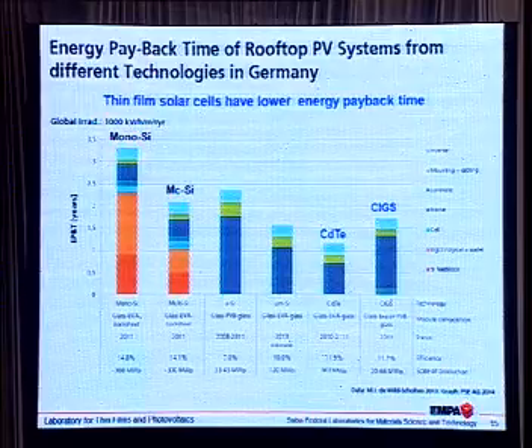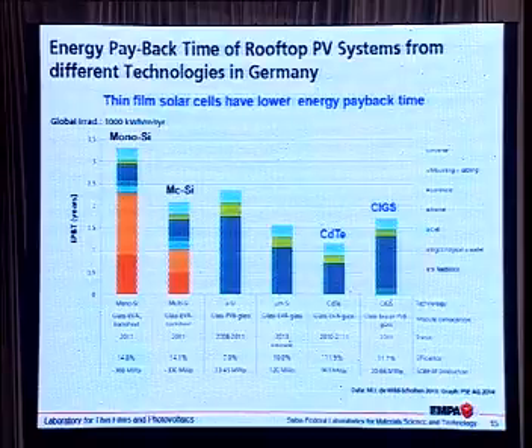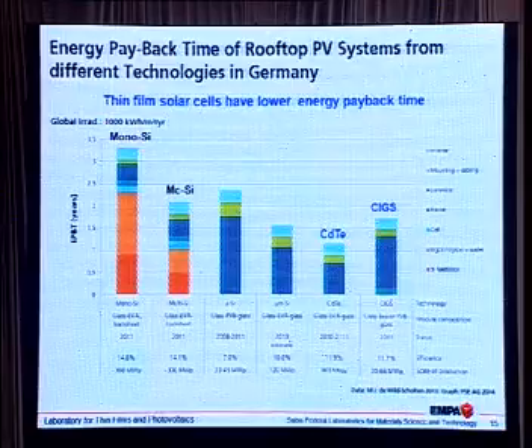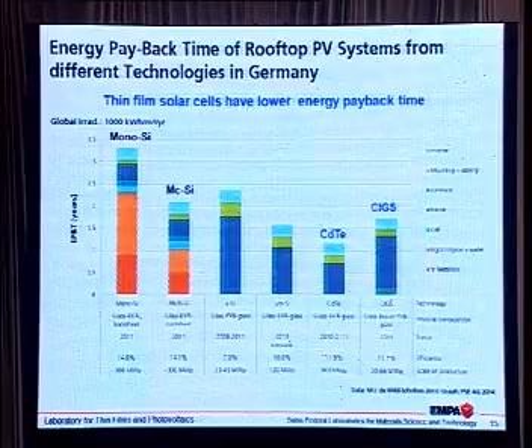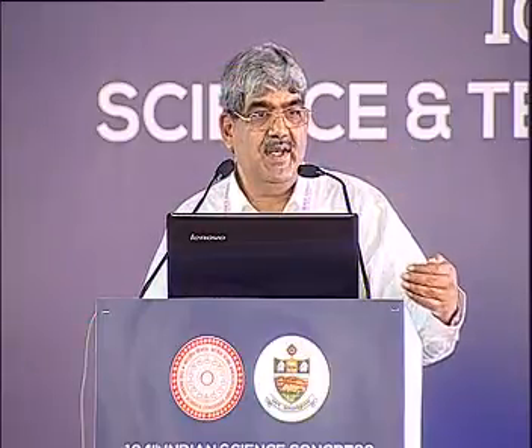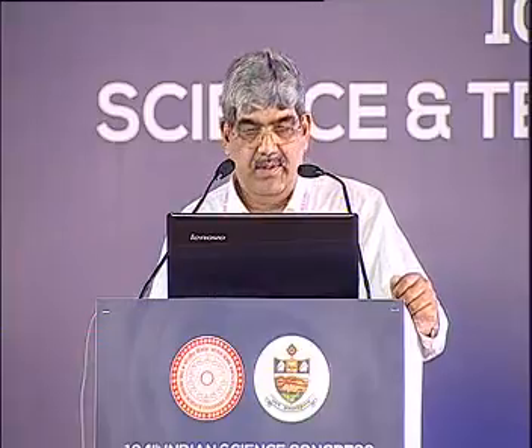The energy payback time of cadmium telluride or CIGS thin film solar modules are significantly lower. They are typically 1.5 up to 2 years compared to monocrystalline or multicrystalline silicon, which is typically about 2 to 3 years when the efficiencies were still low. So what we are comparing is about 15% single crystal silicon versus about 11 or 12% cadmium telluride. So despite lower efficiency of thin film solar modules, they have shorter energy payback time because they take less energy to produce. It takes a lot of energy to purify silicon from sand to make an electronic quality silicon. So this is what is about the energy payback.